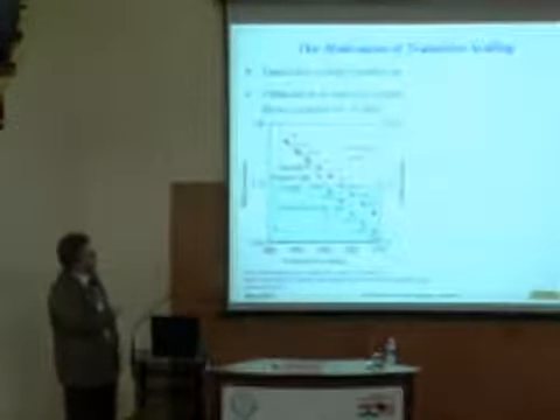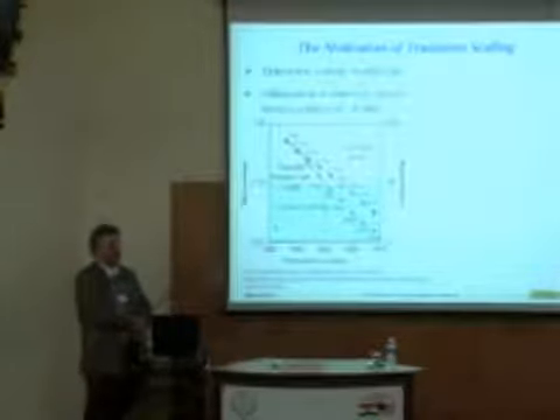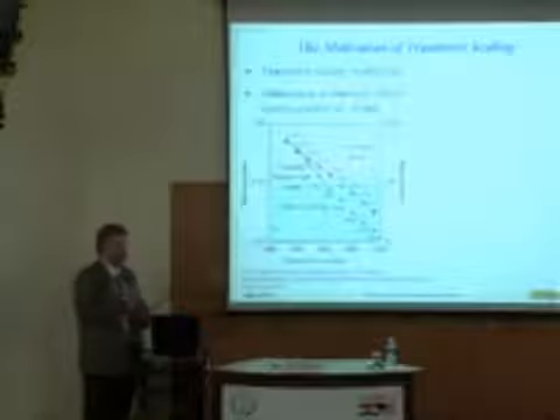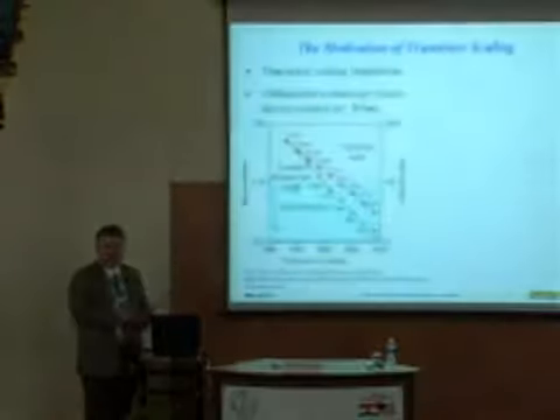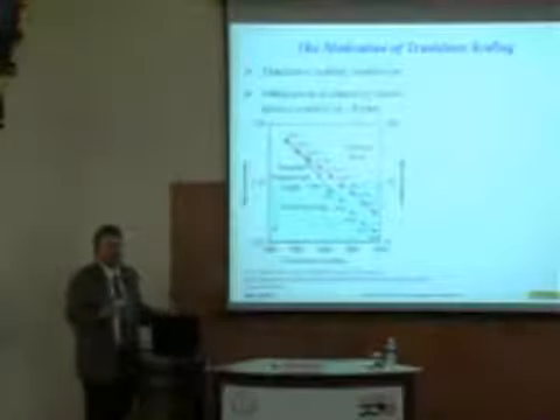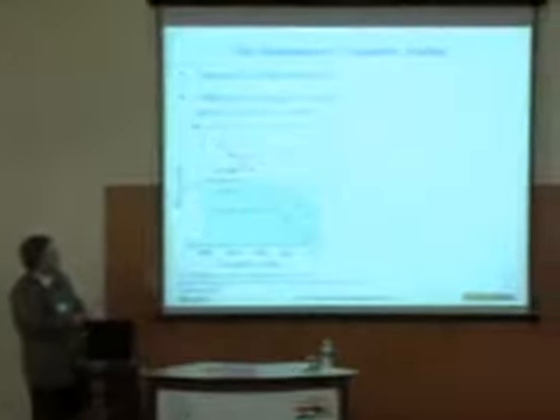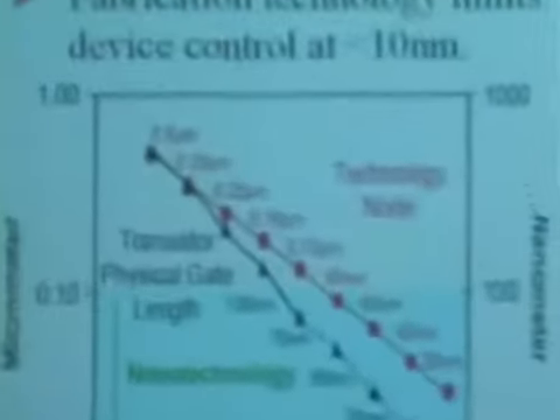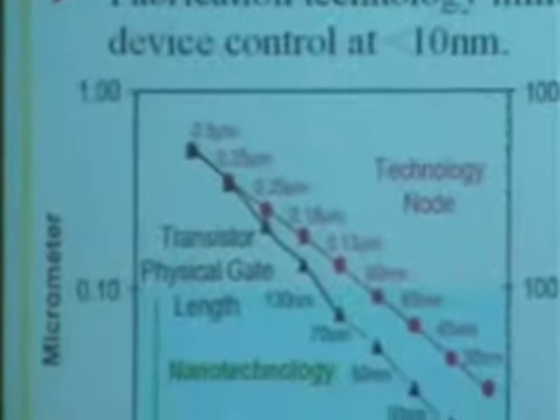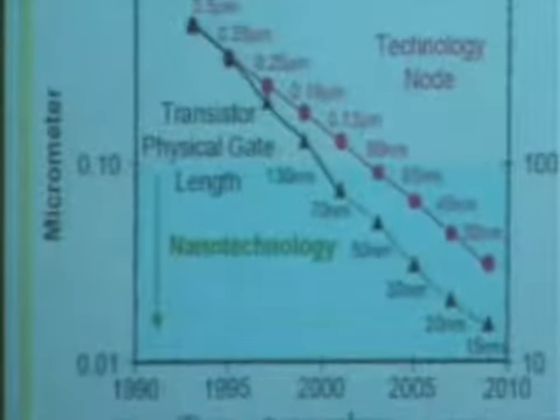As we see, currently production is at 65 nanometers. I mean, at 300 millimeter substrates, they are producing 65 nanometer features, which is a remarkable technological feat. This is being done primarily by Intel, but it's being done also by companies like NEC, IBM Corporation, Texas Instruments, a very wide host of companies in the field, Samsung as well. And what was recently announced was the full demonstration of 45 nanometer technologies. This is actually real gate lengths in these devices.